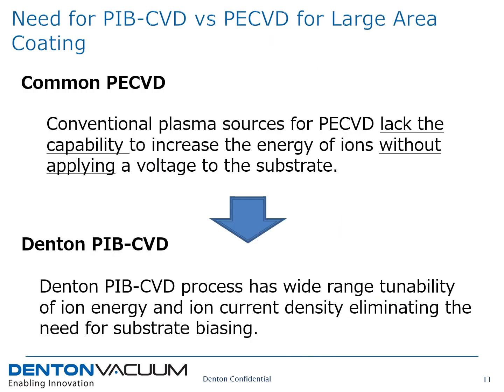Thus, the PIB-CVD process using Denton's linear ion source is more advantageous than conventional PECVD systems, because in order to get higher ion energies in PECVD, the substrate has to be biased, and substrate biasing can lead to thickness non-uniformities, especially when the substrates are insulating, when they are not flat and have inherent thickness differences, giving rise to differences in the electric field uniformity. So the PIB-CVD process has greater benefits for large area coating.